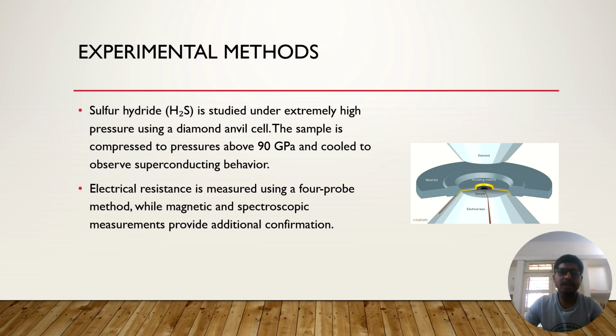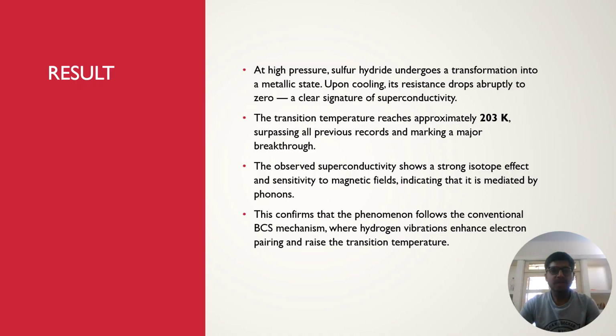Spectroscopic techniques such as Raman spectroscopy are also used to probe structural changes and identify possible phase transformations under pressure. Together, these experimental methods provide strong and consistent evidence for superconductivity in sulfur hydride under high pressures. At high pressure, sulfur hydride transforms into a metallic phase.